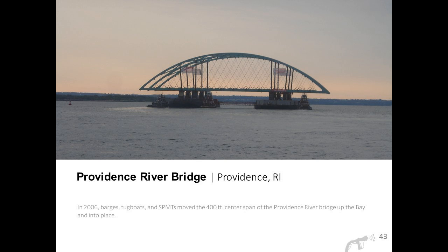Providence Bridge was a project in, again, Rhode Island. Massachusetts, Connecticut, and New York have been using metallization for quite a few years. One of the advantages of having a metallized bridge erected off-site, fully coated, is that in this case the bridge was metallized and fully painted, and any damage that was done was easily correctable before it went to the site. It's a very inaccessible project to deal with after the fact. So the owner and the contractor decided to use metallization and paint, floated it in, and dropped it into place.